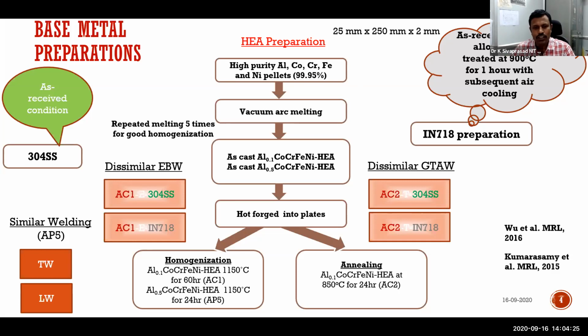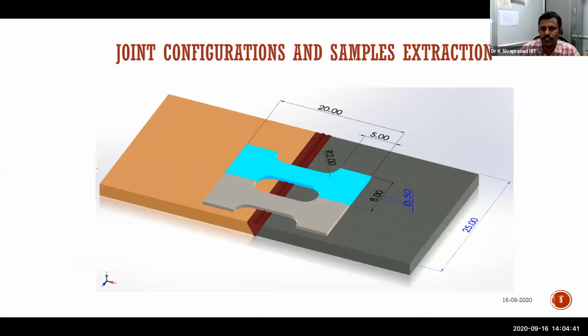Then it is rolled down to equivalent to 2.5 millimeters thickness. Then full annealing was done. Then this homogenization followed by full annealing, one more time it is done. Finally, when we have seen the microstructure, it is an equiaxed grain structure, and XRD shows that it is a single phase.